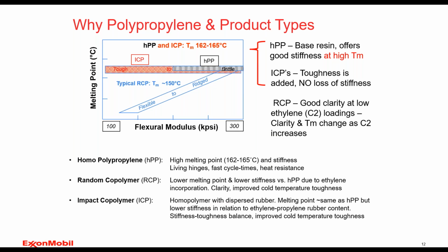I'll touch on what is the foundation of polypropylene and why it's so value add or valuable to, in particular, the injection molding market. There's, again, the three different types: the homo, the random, and the impact copolymer. I mentioned the Ziegler-Natta catalyst system earlier, and different catalyst systems have different melting points, but at least in this case, I'm showing a 162 to 165 degrees C melting point. That is the key to stiffness. The higher the melting point, usually the higher the stiffness, and it has fast cycle time and good heat resistance.